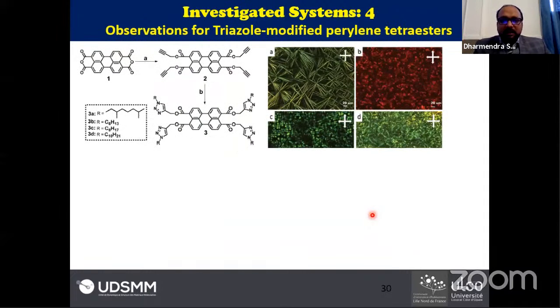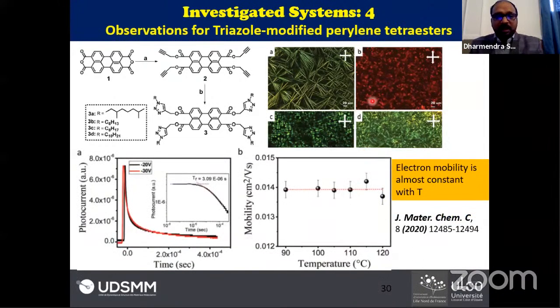Later on, he synthesized again some triazole-modified perylene-based system, because perylene-based systems are very cheap as compared to the previous systems shown for discotics. And he varied the alkyl chain length, and he saw the variation in the mesophase. And we again did charge carrier mobilities for these compounds. We found that yes, if the molecular architecture is heavy or bulky, we obtain a dispersive type of transient curve. And for this, we also obtain very fantastic mobility for this compound. And the electron mobility is again almost temperature invariant. We recently published this paper in Journal of Materials Chemistry.